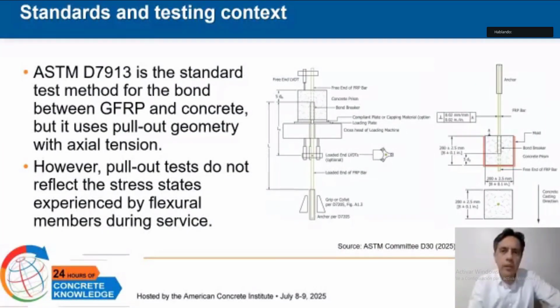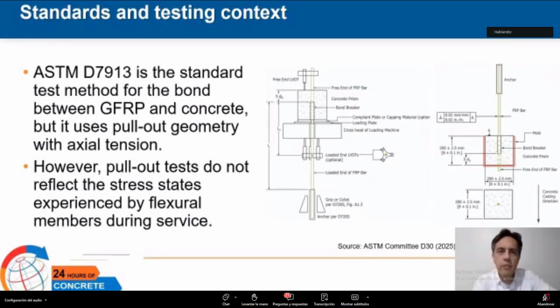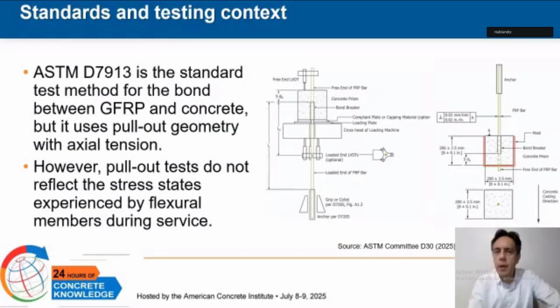The bond between GFRP bars and concrete is traditionally tested using the ASTM D7913 pull-out method. Although this setup is standardized and widely used, it creates stress conditions that differ from those experienced by real structural members. Typically, it applies a uniform axial pull to the bar, failing to account for flexural behavior, cracking patterns, or confinement effects.